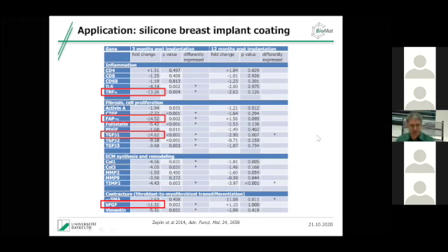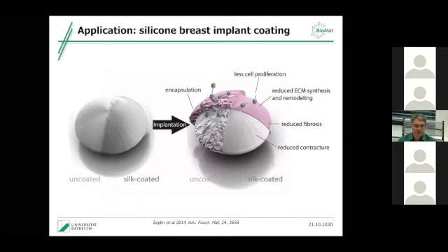So we have a long list, and this is very positive, because this led us to the model, which was now confirmed in human beings, that if you have a silk coating, and this is here just done to make it much clearer, because obviously we will coat the entire implant for the real thing. But here we just coated half of the implant to show you the differences, what happens on the surface. On the silk surface, we have no cell proliferation, reduced extracellular matrix synthesis, no fibrosis, reduced contracture. So this looks much nicer than the other part. And this nicer surface, of course, has the benefit that we have less severe side effects. We don't see any fibrosis, for instance, in the patients.